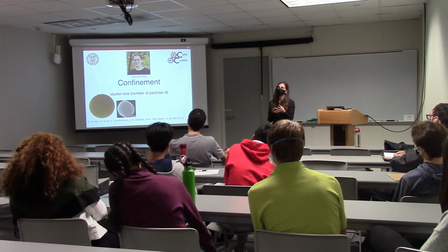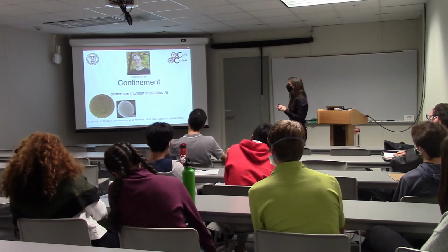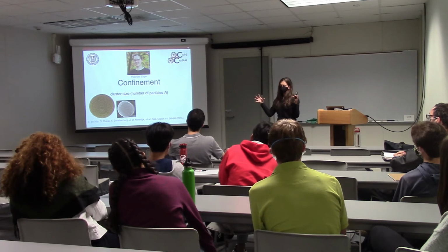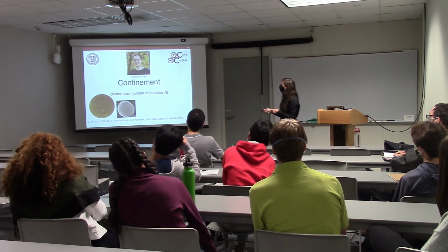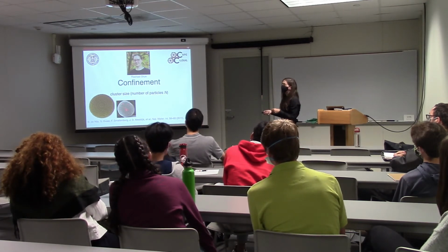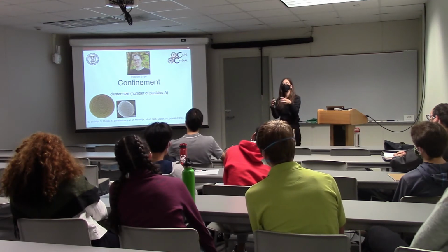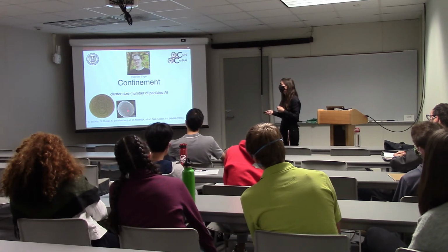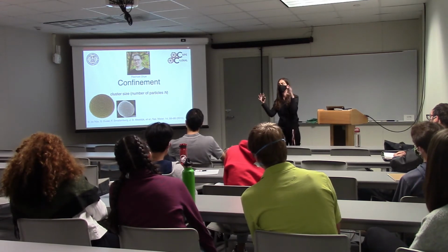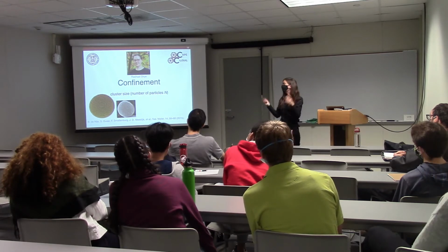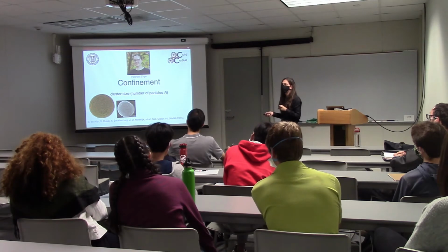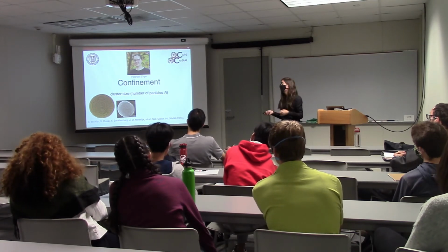Hard spheres were found to form FCC, the closest cubic packing. But if you form them in a very small system, they actually form a twinned arrangement, an icosahedral twin of these densely packed domains. Locally the structure is still the same, but you have these big twins so that you don't have something completely pointy and anisotropic. At around 100,000 particles is when they start forming single crystalline assemblies, so actually pretty large numbers.